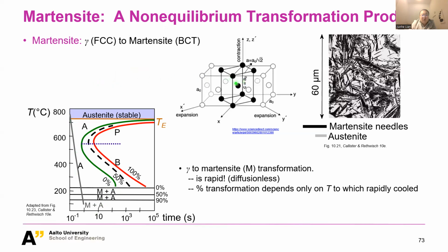That's why martensite has this unstable structure, which is called BCT, that is able to contain the supersaturated carbon in the structure, because we cannot have BCC. Remember, BCC can have only a carbon solubility at room temperature below 0.02%. That's why we have to get this martensite.